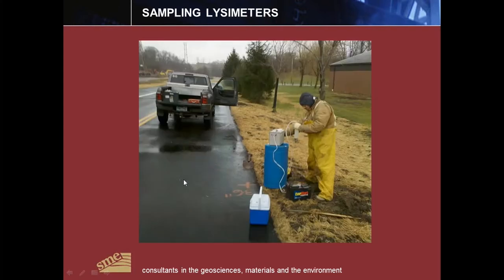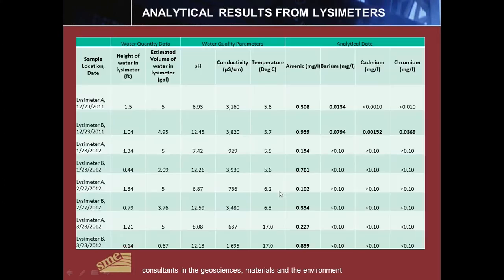As part of the study, we collected water samples in our lysimeters, the groundwater that flowed through the base course. The lysimeters are located beneath the pavement in this area. We have a collection tank just outside the pavement that we can insert a hose into and pump the leachate out of our containers. Once the samples were obtained, we measured the quantity of material taken out, the temperature, the conductivity, and then we sent these to an analytical laboratory and tested them for the heavy metal constituents.